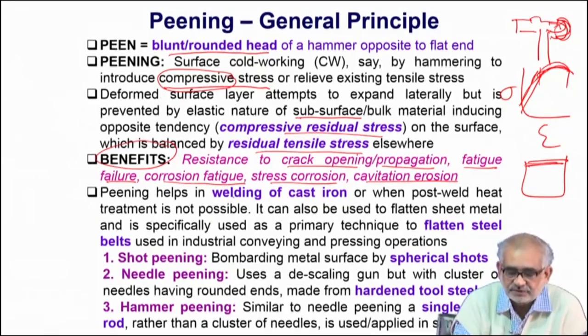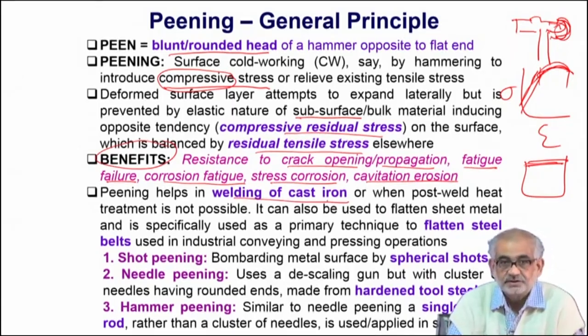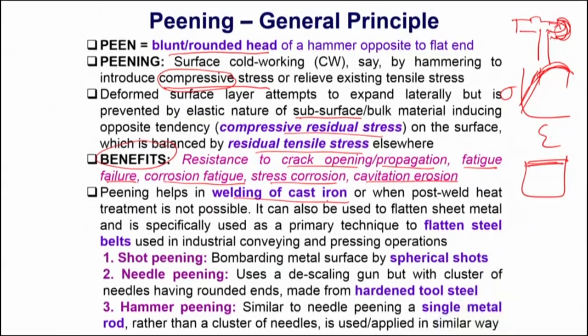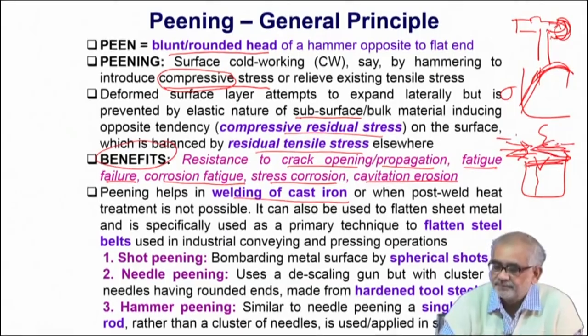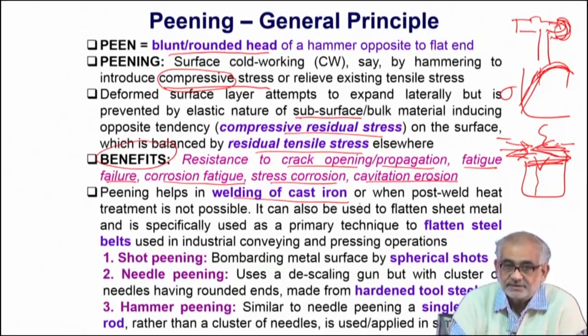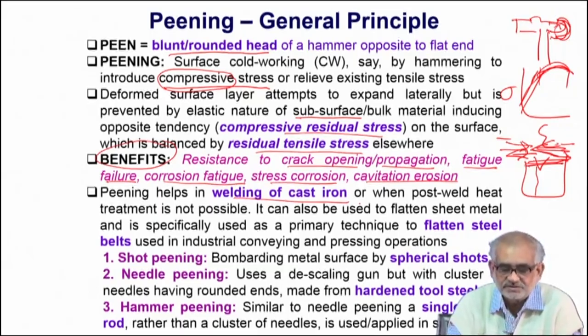In certain manufacturing operations such as welding of castings where no post-weld treatment is possible, when liquid solidifies in any fusion welding process the state of stress on the surface is tensile in nature, which is not conducive for greater fatigue strength. If there is a crack on the surface under residual tensile stress, the crack can easily open. We would always prefer compressive stress, acting towards each other. For a welded zone, particularly at the root, creating residual compressive stress by hitting with ultrafine spherical balls is beneficial.